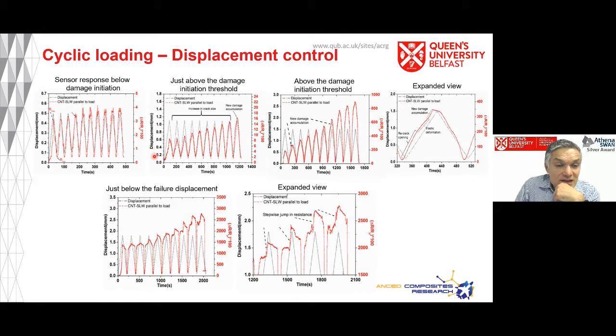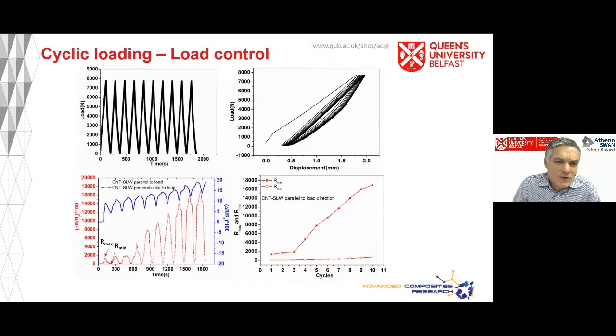Now, you can see that if I then start loading at a much higher displacement, I'm starting to induce damage, and that damage, the inducement of permanent damage, is manifested by an increase in resistance that I'm measuring through that carbon nanotube web. And if you look closely at the features of the response, you can actually look at such things as whether the damage is the result of crack reopening or elastic deformation or the creation of new damage. So again, quite a sensitive damage sensor.